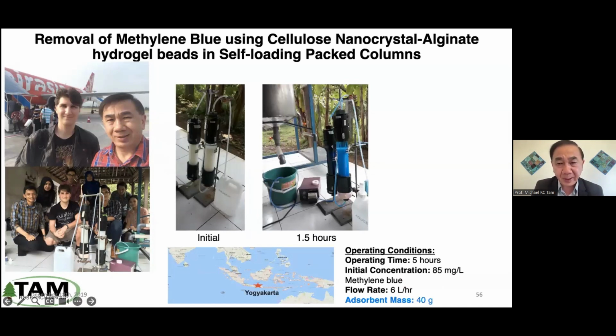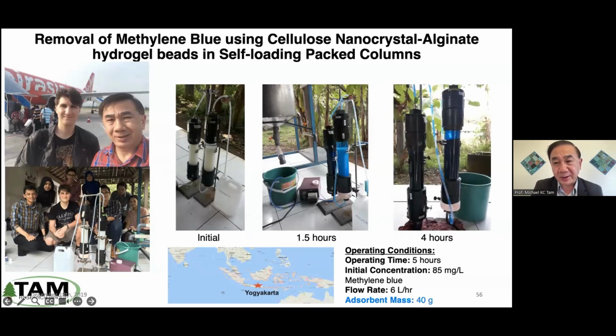As you can see, this column is very dark blue, and eventually all the dyes are removed by our column. And at the end of the experiments, what we found is that we can now retrieve these beads and compress and recover the concentrated dye. And these dyes now can be reused by this batik treatment of the textile. So the advantage of our system is we can recover the concentrated dyes, whereas activated carbon, you cannot. You have to just incinerate the dyes.